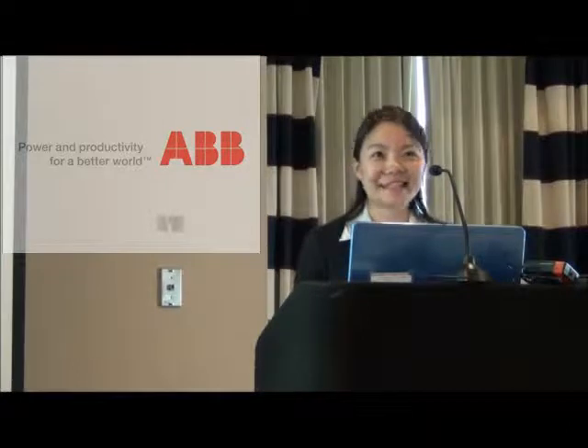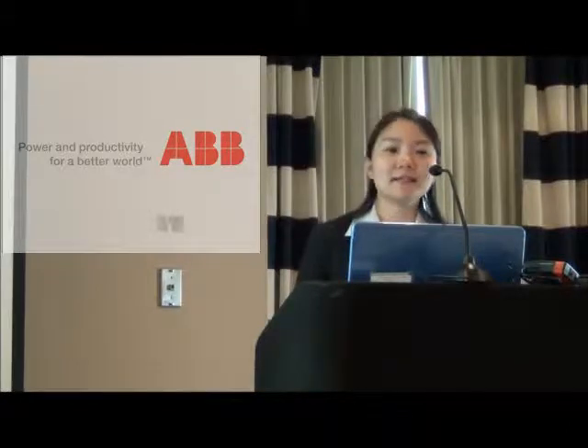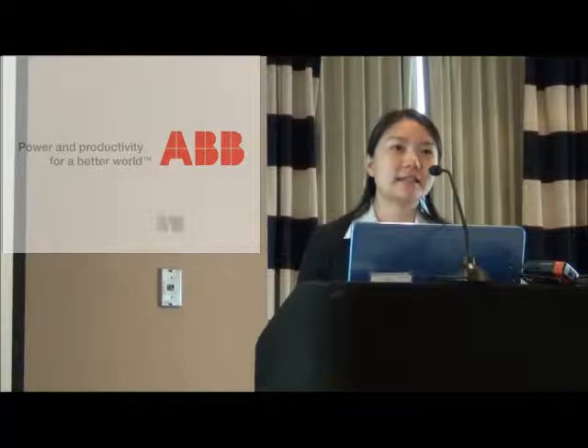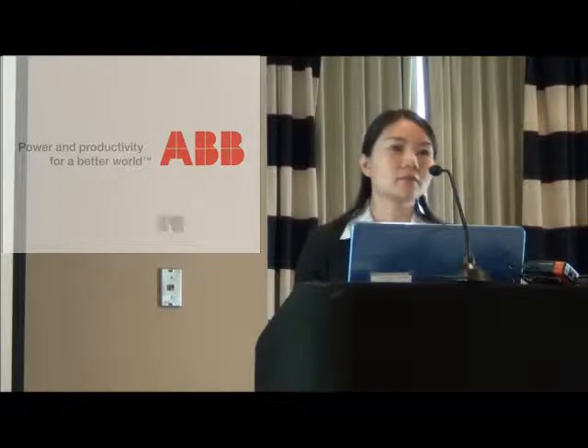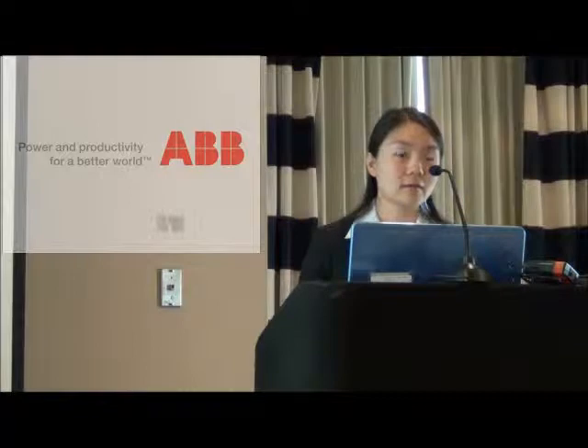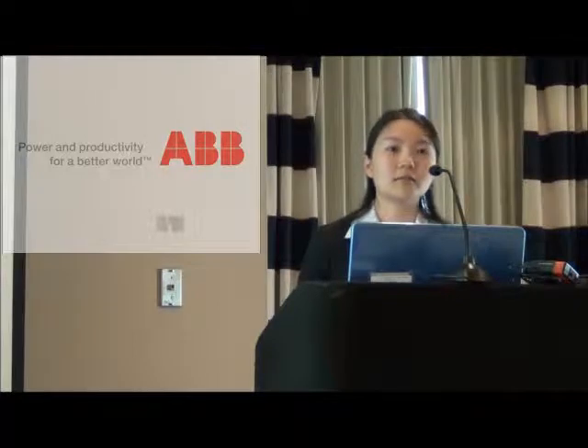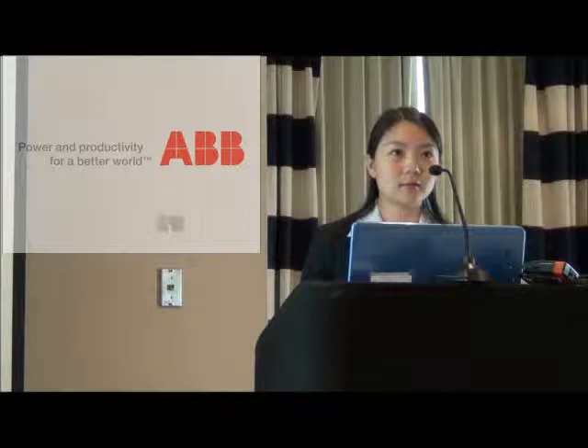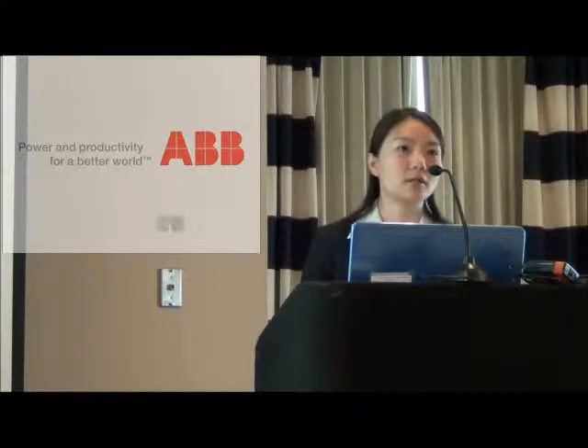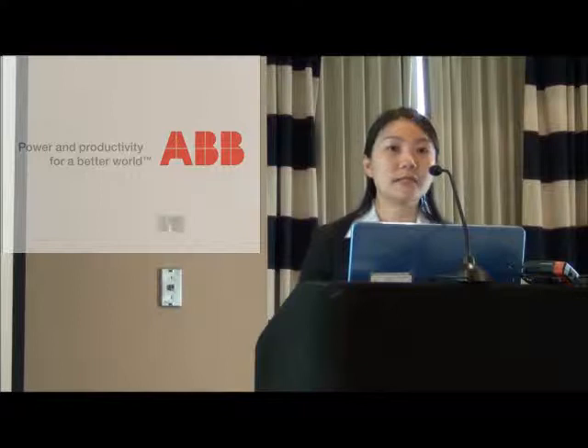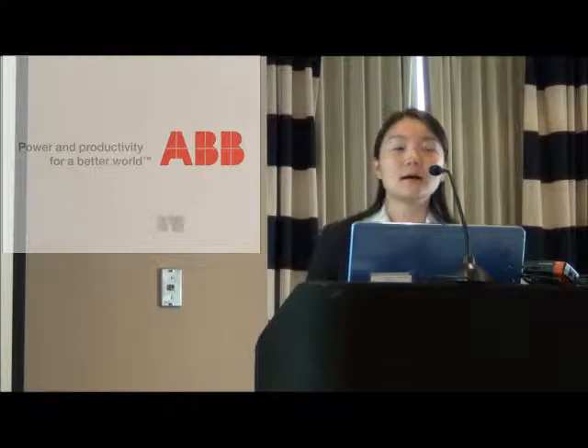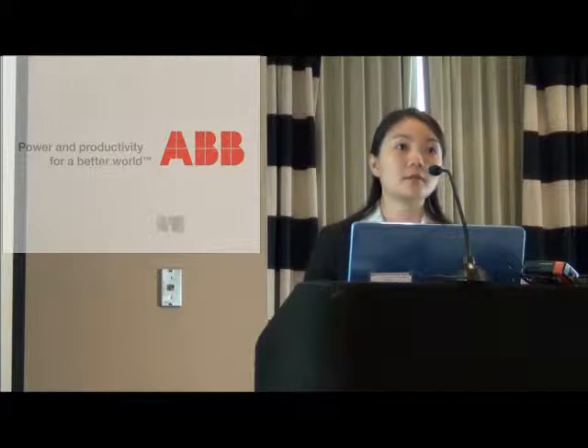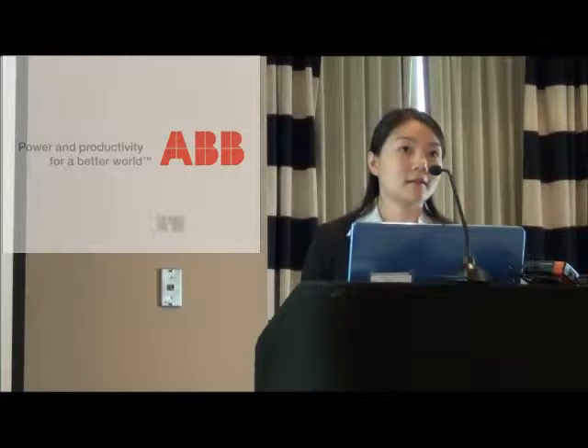So that's the reason - when we did the test, that sample geometry was developed by Professor Keith Nelson at RPI, and he did a lot of research on the techniques we should use, so we used that geometry. There was only one available, and it was easier to cast at that time. But we noticed it's not a perfect geometry for epoxy - it's better for thermoplastic in that geometry.